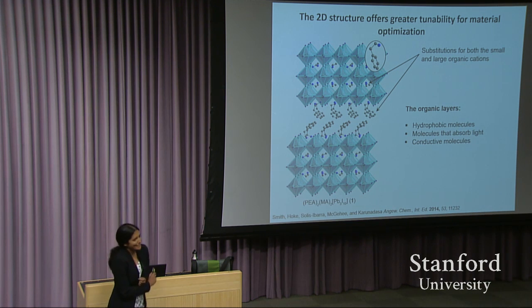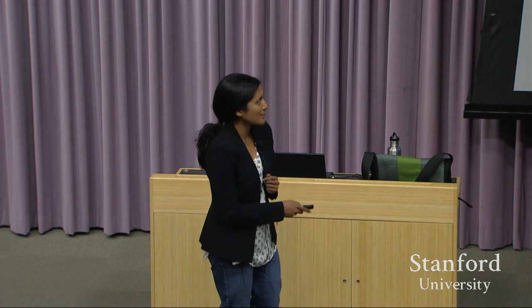But the fact remains that if you throw the 2D perovskite into a bucket of water, it will decompose. So we didn't make it waterproof. We just gave it some more time. We made it a little more moisture resistant. So it's still a concern that the material degrades to PbI2, and PbI2 is water soluble.